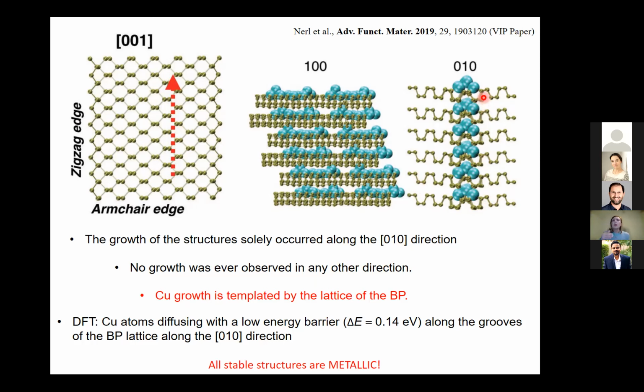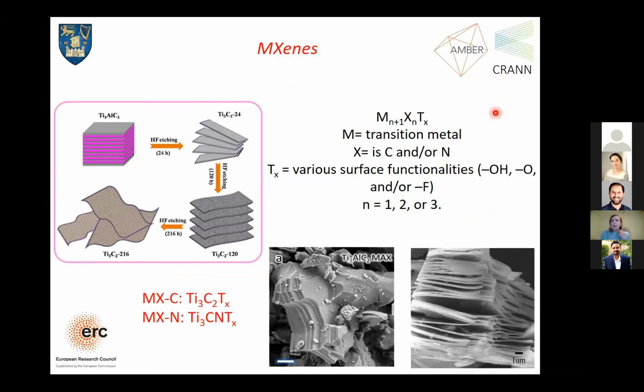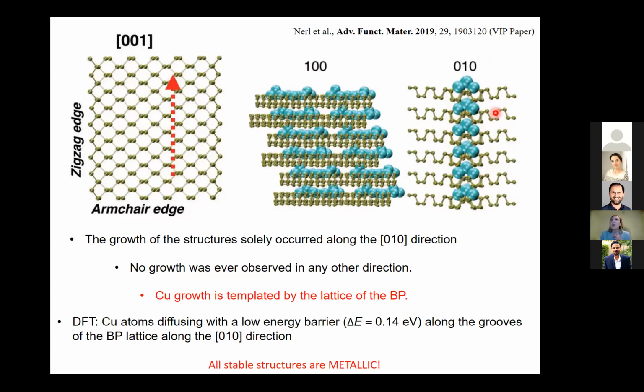And we also realized from DFT that copper atoms were diffusing with a very, very low energy barrier, about 0.14 eV. And I think the most interesting finding, which we are now pursuing from a devices perspective, is that any structure that at the end was deemed stable was always metallic. So this was a huge advantage, and something extremely unexpected. And this has, again, given us a very nice twist. We are in the process of using this for templating devices, because it gives us some unique opportunities to have really a 2-line thick metallic wire being built on black phosphorus.